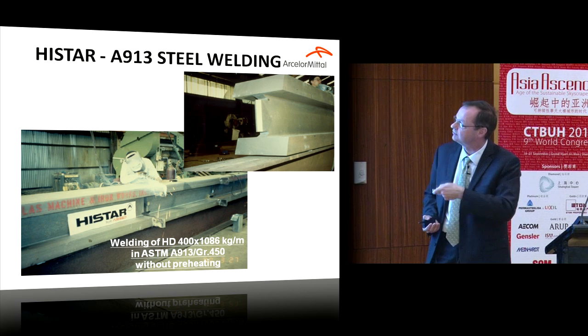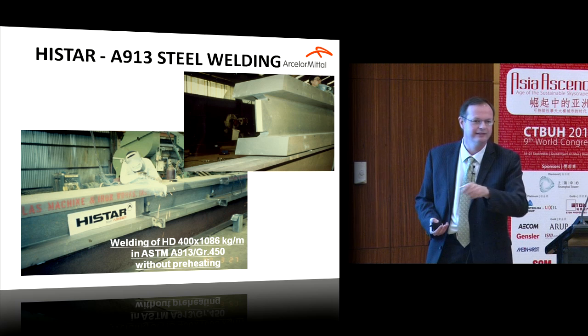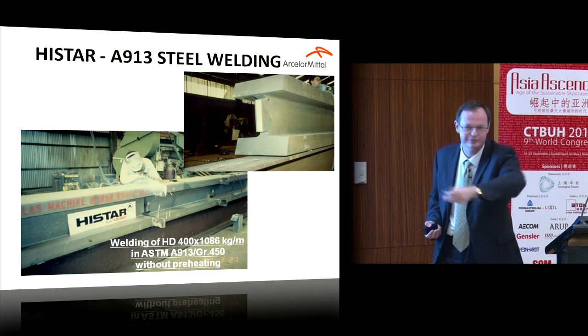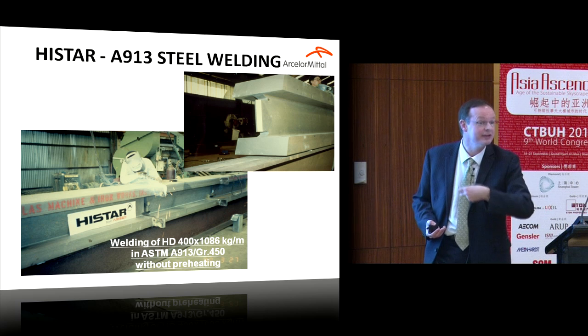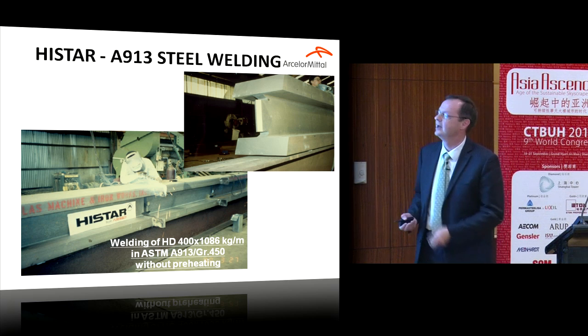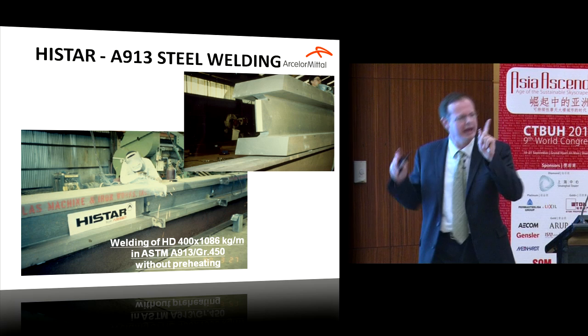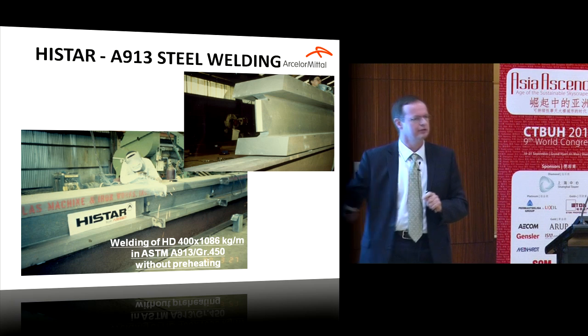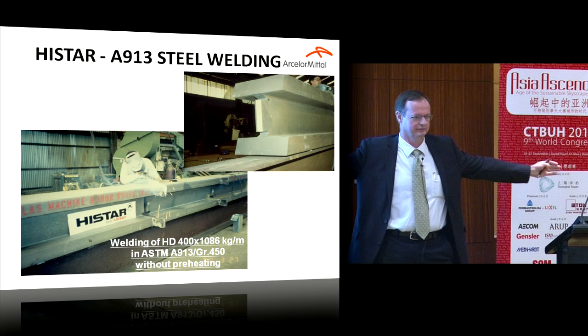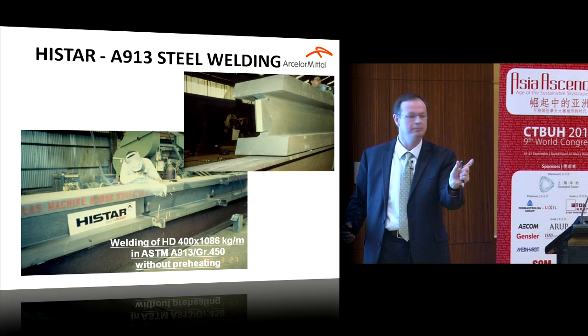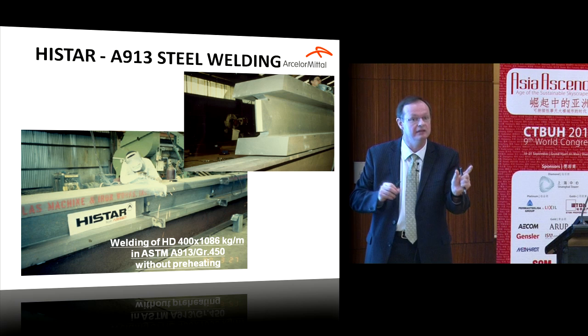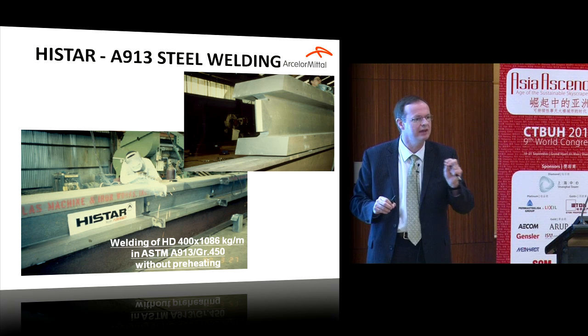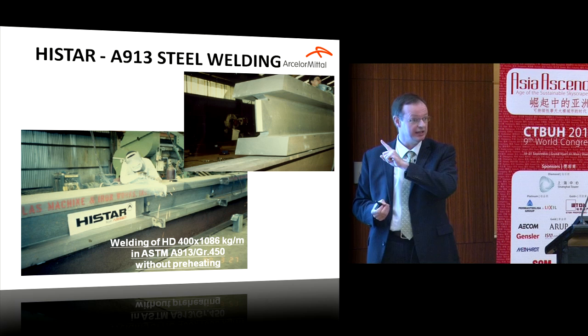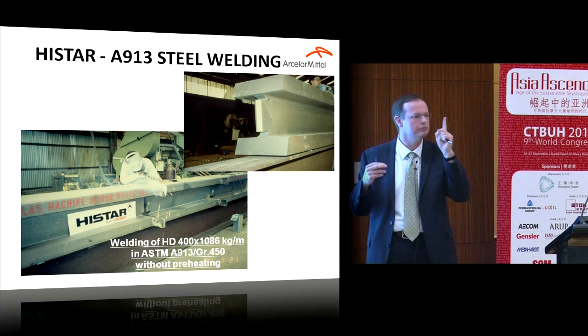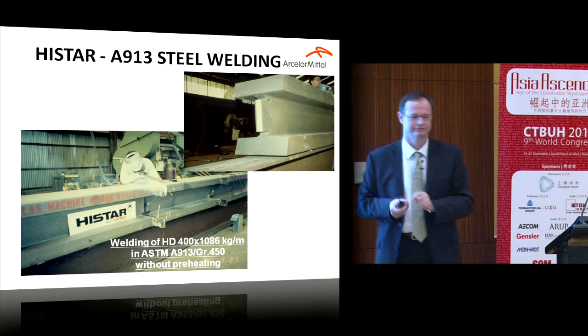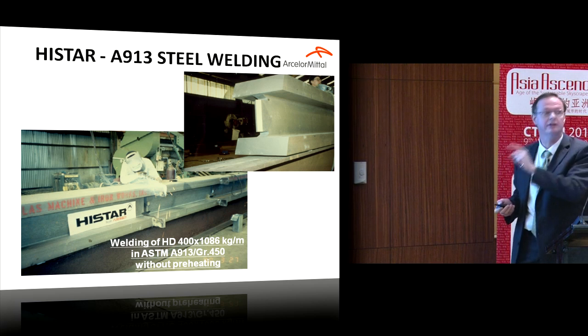And then to do the welding of that, do you know how many passes you need? Can anyone guess? It's 140 passes. So it's a lot, right? And it takes about 8 hours for one jumbo like this. Now imagine the huge caissons, because they are also using 65 mm plates. To do the welding, if they really follow the rules, it will take days. And I checked, I came 2 days ago, they did one in one night. One caisson was welded during the night.